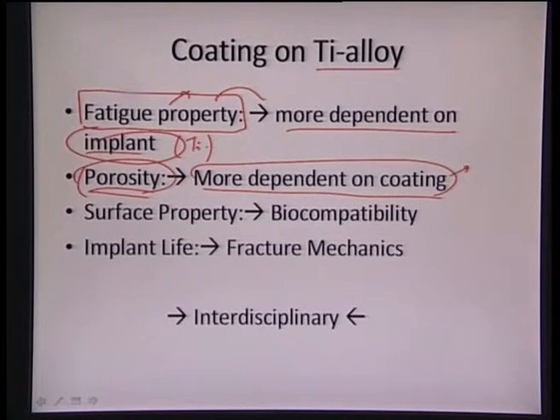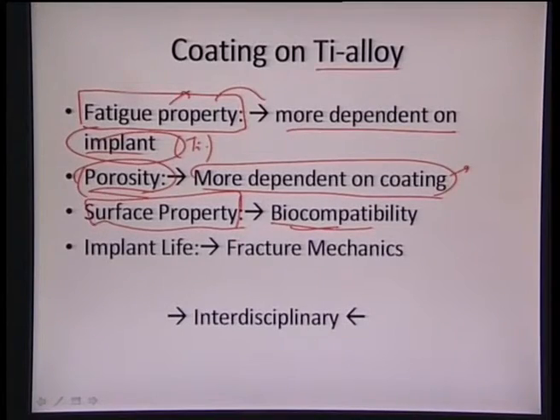And again, this surface coating is highly responsible for biocompatibility, because the surface is the one which comes in direct contact with the cells. So if the surface itself is not biocompatible, we will see some toxic effects. Cells may not tend to adhere to the surface, cells may not proliferate, cells may not grow at all on the surface. So we see that surface property is highly essential in dictating the cytocompatibility or the biocompatibility of the particular material. So a secondary coating can be applied on the titanium alloy to make it much more biocompatible.